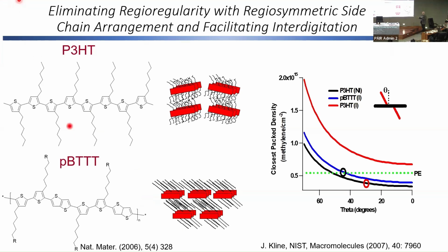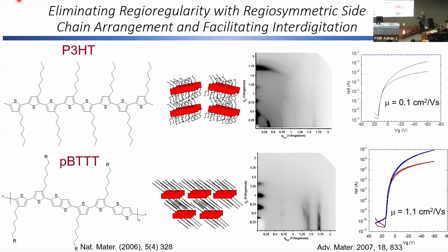And we can see here that when we look at the close pack density, PBTTT here is in blue, we can see that there's an angle of side chain projection of around 45 degrees, where this number now matches perfectly polyethylene. And this actually is the tilt angle of the PBTTT side chain. So it projects that angle and it perfectly forms a very high density and very coherent side chain interdigitation. And why does that matter?